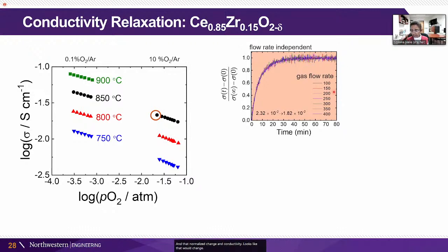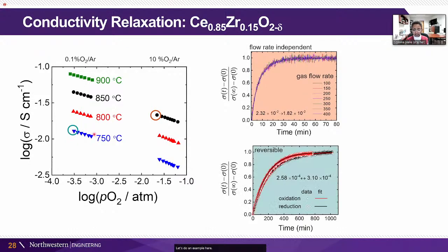We change the gas flow rate just to make sure we're actually measuring our sample and not the chamber, for example. And we can see these all line up. Great. Let's do an example here. And this is just to show you that the forward and reverse are also the same in this normalized conductivity plot. That's important because we're assuming a linear response. So we need the forward and reverse to be the same. Again, it tells us that our step change is small enough.